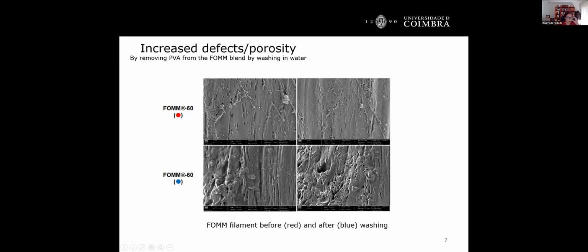This is the micrographs of the FOMM filament before and after being washed in water. As you can see, we have already increased the defects, in this case the porosity, of the filament itself, which means that once you have the components 3D printed with this material, you will end up with a hierarchical porosity. So you have the macro porosity, which is given by the layer height you choose, and you have a micro porosity, which will be enhanced by the removal of the PVA.